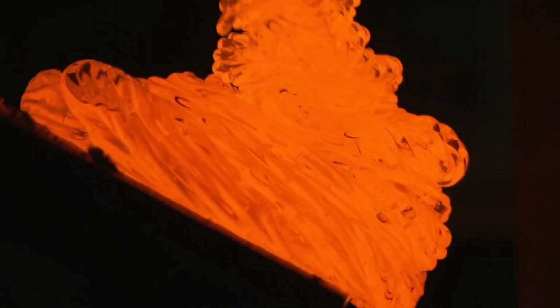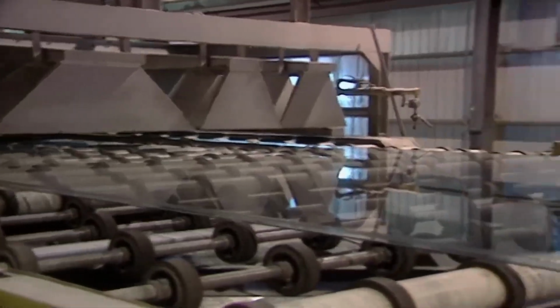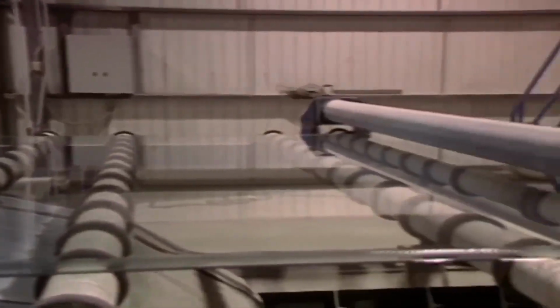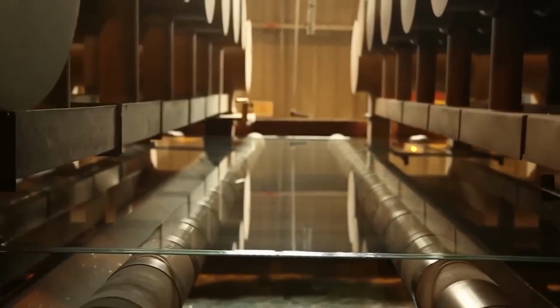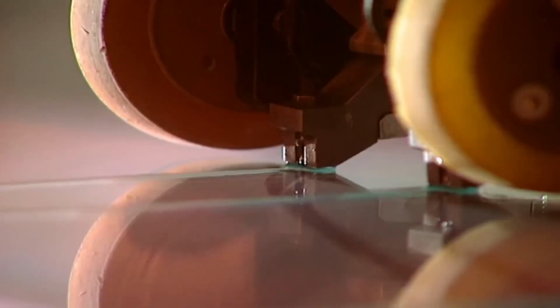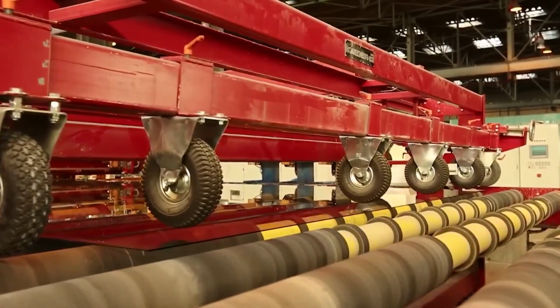Once the raw materials have melted completely, the liquid glass flows onto a long, shallow bath filled with molten tin. This process, called the float glass method, was invented in the 1950s and revolutionized glass production worldwide. Before this, glass sheets were rolled or polished by hand, often leaving small ripples or distortions. The float method solved that problem because molten glass floats naturally on the denser molten tin. It spreads evenly under its own weight, creating a perfectly smooth surface on both sides. Fire polishing burners above the bath heat the top layer, smoothing it further, while gravity keeps the bottom flawless. As the glass moves slowly forward, it cools and solidifies, forming a continuous ribbon that's flat, strong, and crystal clear.